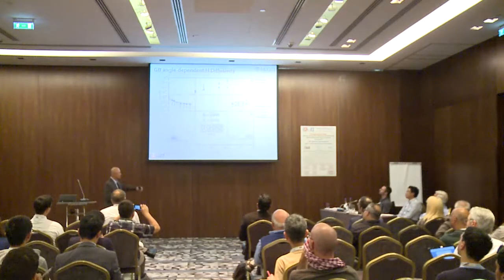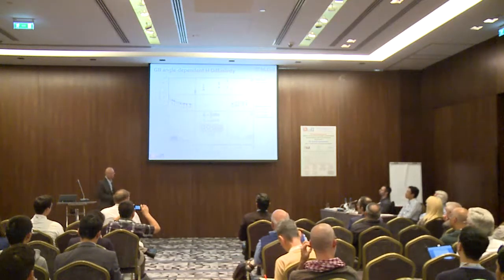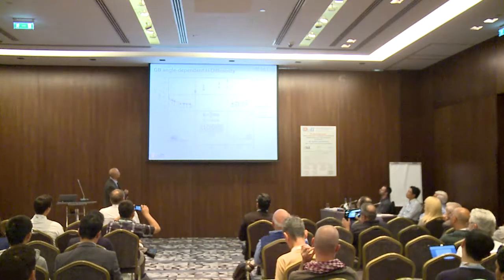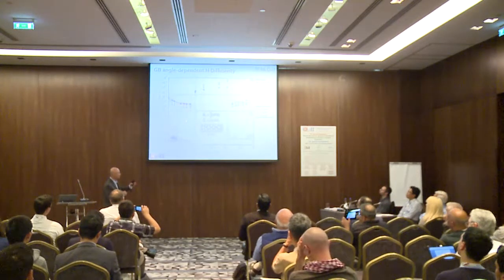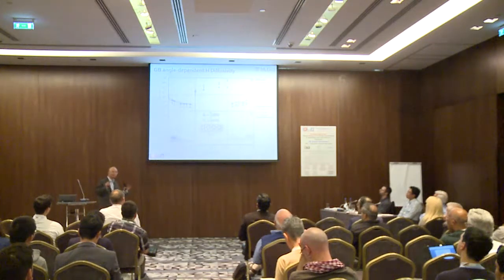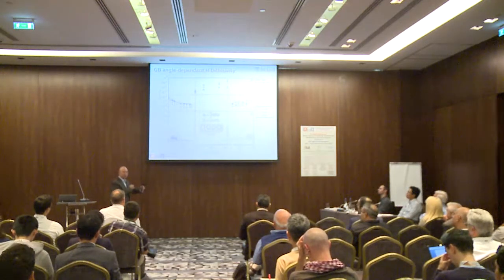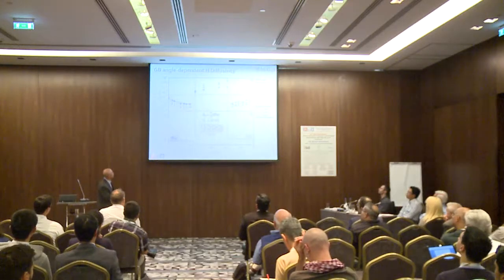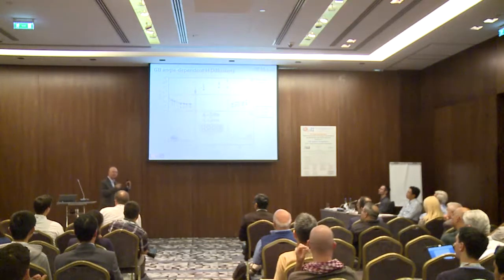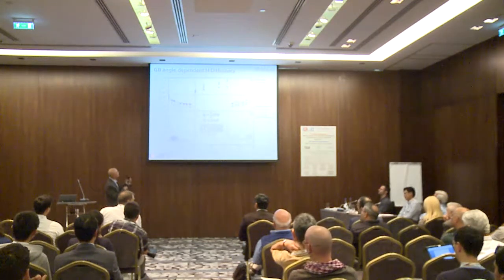Okay, with that, that basically concludes my talk. But if I may, I guess I still have a couple of minutes, right? I want to mention that one can easily get carried away by this result, because it's showing slow diffusion or fast diffusion. But we need to be a bit careful when we try to interpret this result and connect it to experimentally measured diffusivity, because what we are measuring is actually the overall diffusivity. So basically, we count all those hydrogen inside the system. The way we calculated it, we take the mean squared displacement for each individual hydrogen.